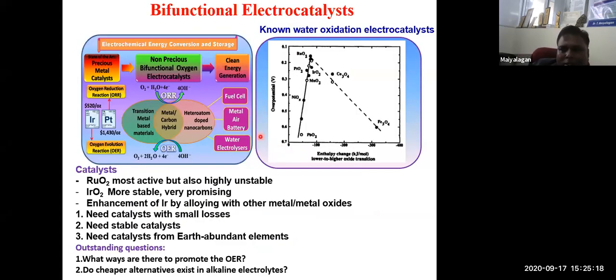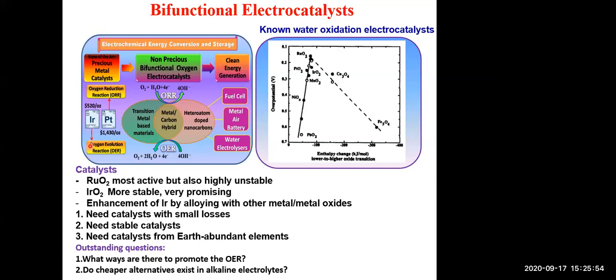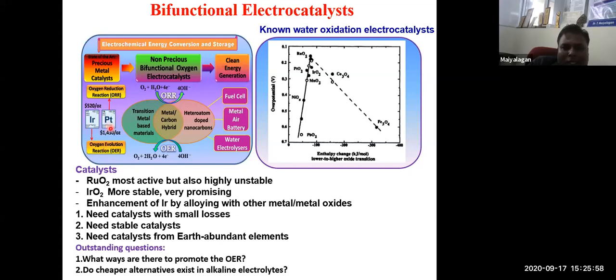What is the status of the catalyst till now? People have been working on oxygen reduction catalysts. Platinum is the best catalyst for the oxygen reduction reaction, and it costs $1,430 per ounce. For the oxygen evolution reaction, the best catalyst is iridium. But these are more expensive catalysts, and when you use them in your metal batteries, you are increasing the cost of the battery. So you want to replace the expensive platinum or iridium with cheaper metals, because your anode is cheaper. In a zinc-air battery, zinc is cheaper; iron is cheaper; in an aluminum-air battery, the aluminum is cheaper. So you want to replace it with some other metal which is cheaper.